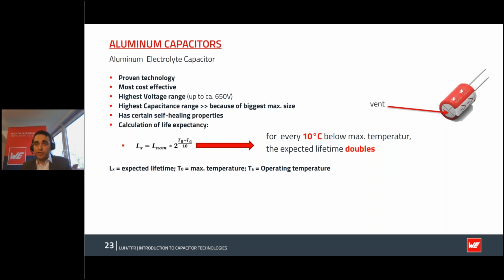So first we go into the aluminum electrolyte capacitor. You can see on the right here, they always have a vent if the size is big enough to have a controlled failure mode here. It's a well-established technology and very cost-effective. As you can produce them in basically any size you want, you have a huge range when it comes to capacitance value and also the voltage range. They do have self-healing properties as soon as voltage is applied. And the lifetime is calculated as you can see here. You need the basic endurance value you'll find in your data sheets, and then the maximum temperature and the actual applied temperature. This formula states basically that for every 10 degrees you stay below the maximum temperature range, you will double the lifetime.